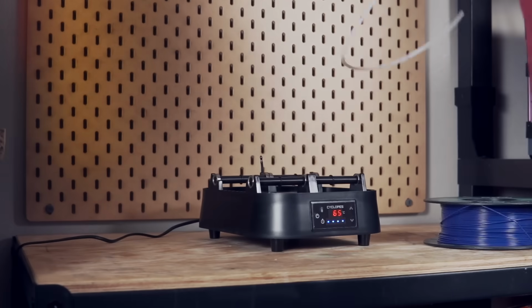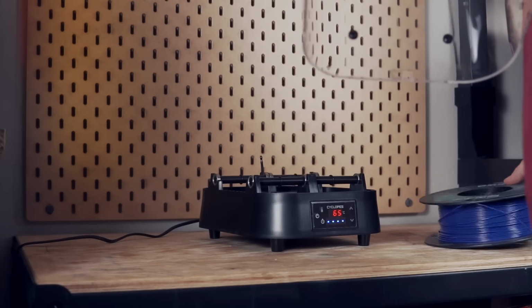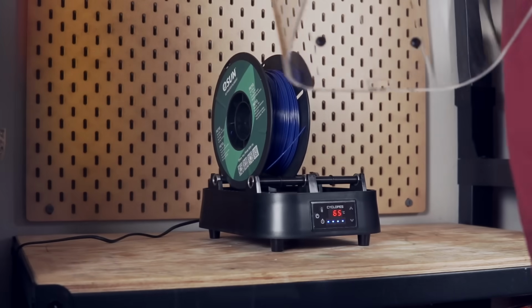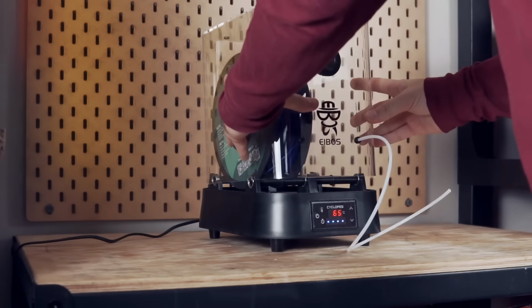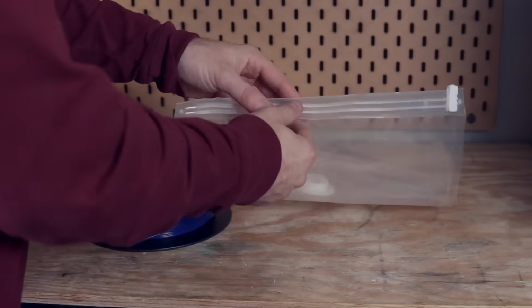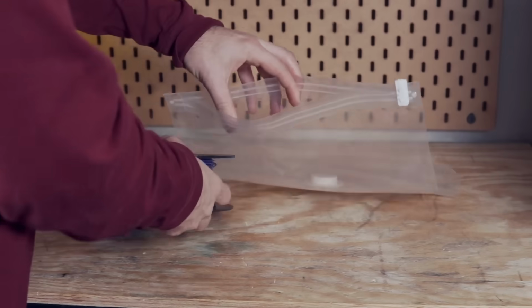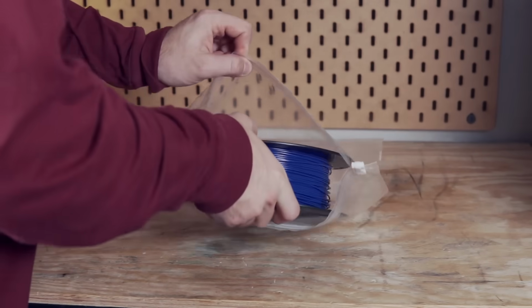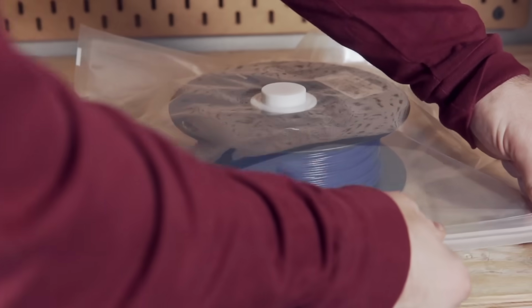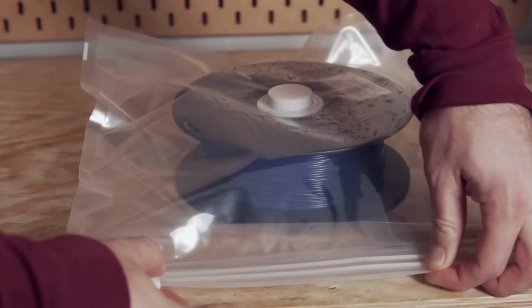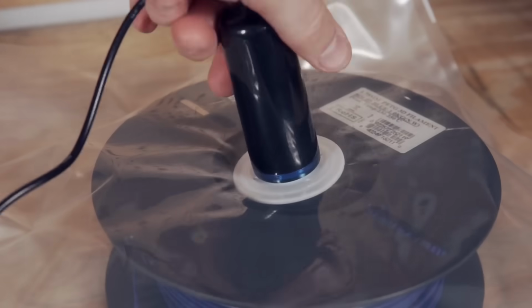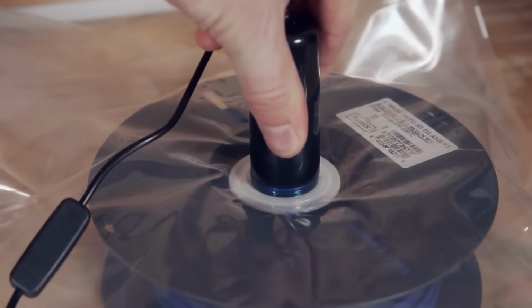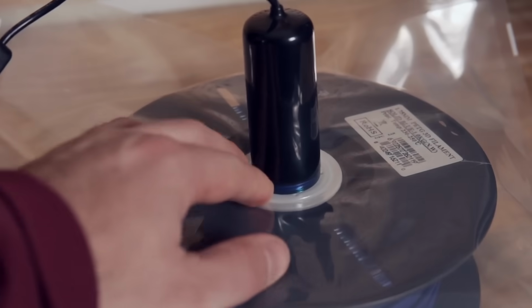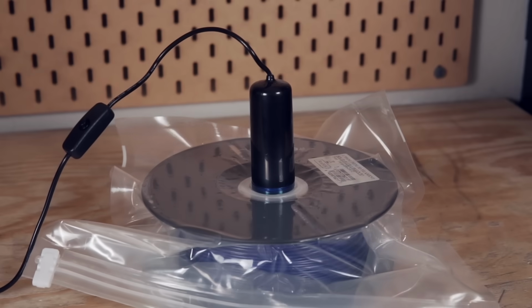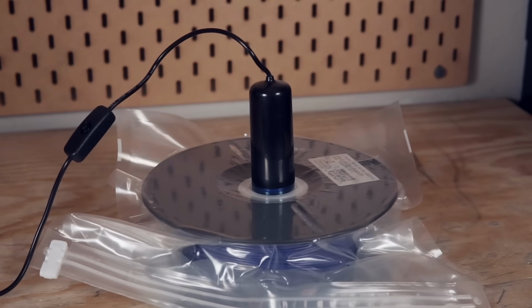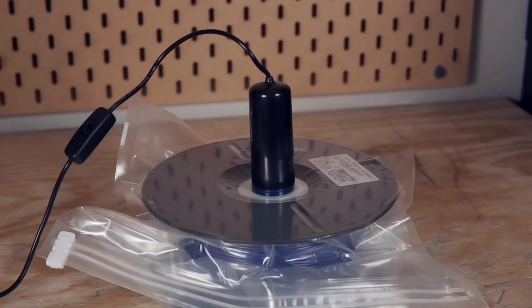I think one was around $50 and one was around $120-ish, give or take. And I can link you in the description down to those, but I recommend, regardless whether it's a new PETG, whether it's an open PETG, that you at least dry it to make sure you're starting from a dry state, because wet PETG is not going to look good. It's going to be much more stringy, and it doesn't matter how good your hardware is or how dialed in it is. If you have wet filament, it's just not going to turn out good. And for anyone that's wondering, my recommendation is I dry out PETG at around 65 Celsius for at least 2 hours before printing with a spool that I haven't used in a long time.